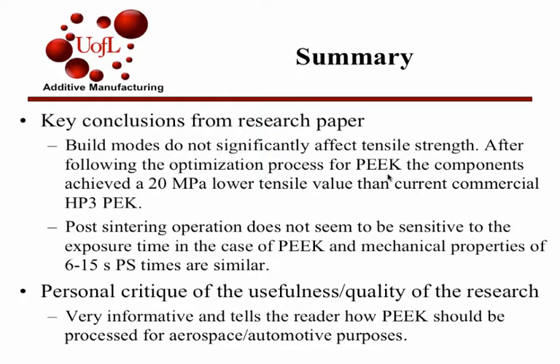In summary, the key conclusions from the paper: the build modes do not significantly affect tensile strength. After following an optimization process for the PEEK components, it achieved a 20 megapascal lower tensile strength value than the current commercial PEK that is used. The paper made it seem as if that was not a huge discrepancy, and within the confines of what the material will be used for, it isn't to them. So I thought that was pretty interesting too. Also, the post-sintering operation does not seem to be sensitive to the exposure time of the infrared light at the very top.